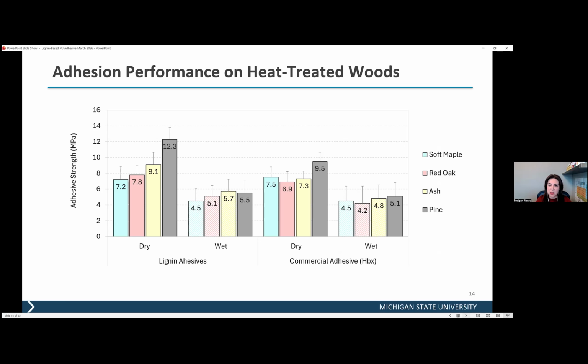What happens is we see some chemical modification of the wood surface. After heat treatment, the wood, doesn't matter which species it is, some of them work better than others, but all of them become more dimensionally stable. And because of these changes in hemicelluloses that we see in the wood after heat treatment, we're going to see some improvements in performance of this heat-treated wood. It has, to some degree, resistance to decay and also insect attack.